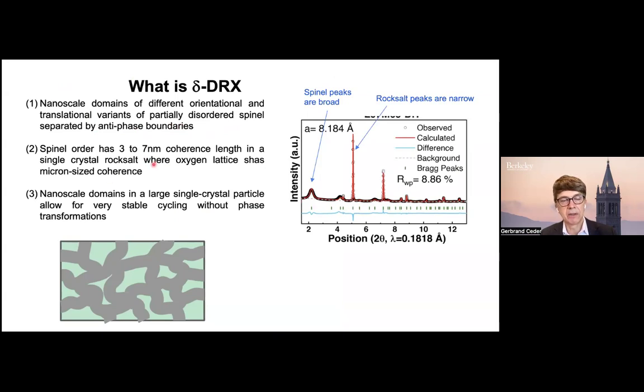The coherence length of these domains is very small, and that's why you don't have a first order phase transition. So we've known for a long time that if you can keep material size small, like nano-sized, then you don't have first order phase transition, so you don't have a two-phase region. But what's maybe unique here is that these are not nanoparticles. These are nanospinel domains in a large rock salt particle.